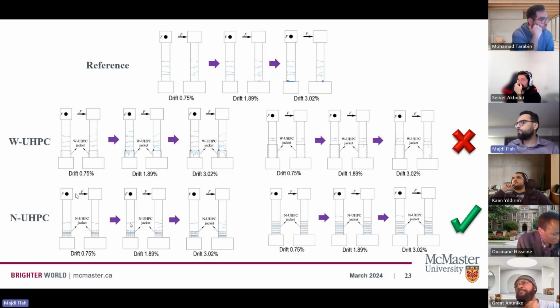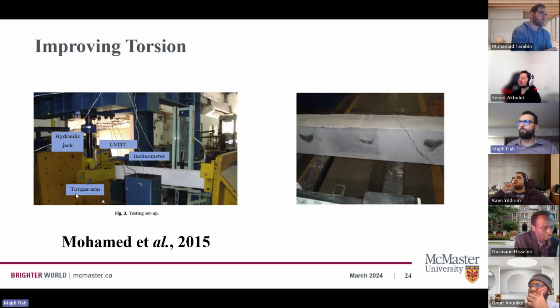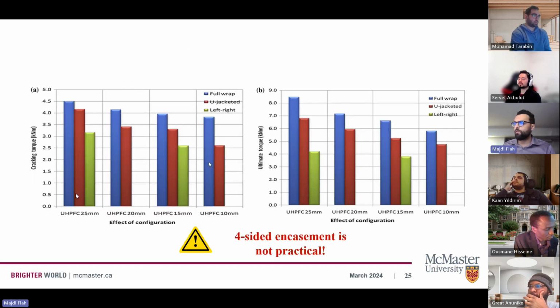For the UHPC, we didn't have this kind of issue, and for this reason, to improve the seismic resiliency, the authors have voted for this kind of repair. Now, talking about torsion, this study tried to investigate beams in torsion. They tried to fully wrap the beam, U-jacket it, or jacket it on the left and right sides, and of course, the full wrapping will yield a better performance, whether for the cracking torque or the ultimate torque. But when I think about it, does it make sense? Is it practical to have a full wrap in the industrial context? Of course not, right? Because it's a monolithic pouring, and the top portion, you don't have any control over it.